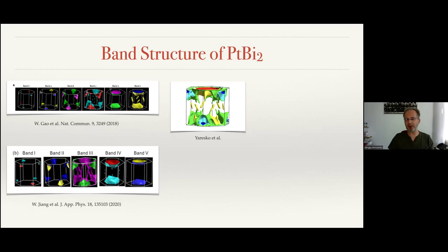there are quasi two-dimensional objects. If one looks at this Fermi surface, one could probably see some kind of layered structure, and this probably explains why the material is cleavable. Because in order to make an ARPES experiment, one has to cleave the crystal, one of the methods to prepare an atomically clean surface. And this is probably the explanation why it is cleavable, although it is very three-dimensional according to the number of bands and the topology of the Fermi surface.